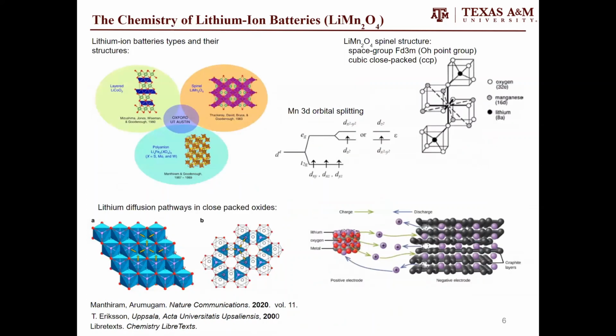The chemistry of lithium-ion batteries, specifically based on lithium manganese oxide. Lithium manganese oxide, LiMn2O4, is a spinel structure of space group Fd3m, an Oh point group, structured in a cubic close-packed array. The oxygen ions are at the 32e position, the Mn ions are at the 16d site and have an octahedral coordination to the oxygens, and the lithium ions are situated at the 8a tetrahedral site at the edge of the octahedron next to the vacant 16c sites. This all contributes to a very strong and stable structure.